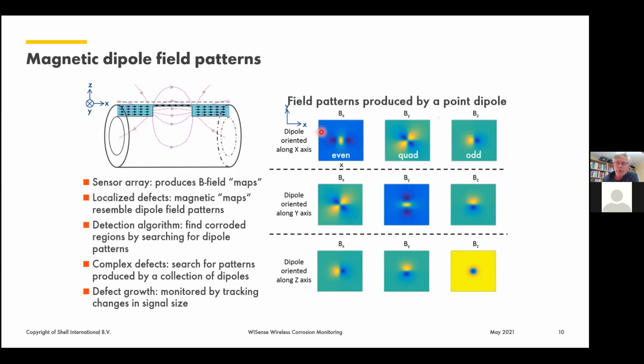In the Bx direction, you see a pattern that is, in the dark blue, a low and then a high and a low amplitude. Sometimes it's called a Mexican hat, a sombrero. Then in the By field, there is the cross, a quadrupole. It is two signals, low in one diagonal direction and two peaks high in the other diagonal direction. Quite characteristic. And then there is the more cosine type of signal, from a high to a low, in the Bz direction. It needs a bit of training to read these signals.